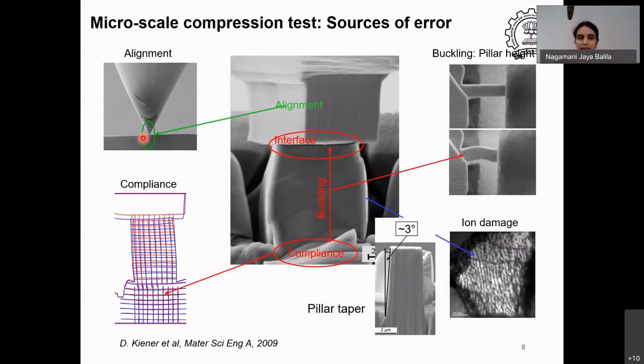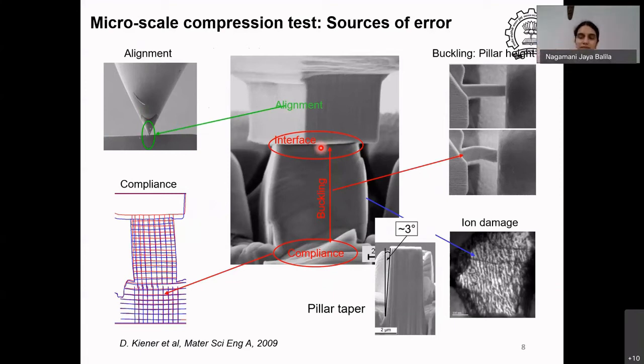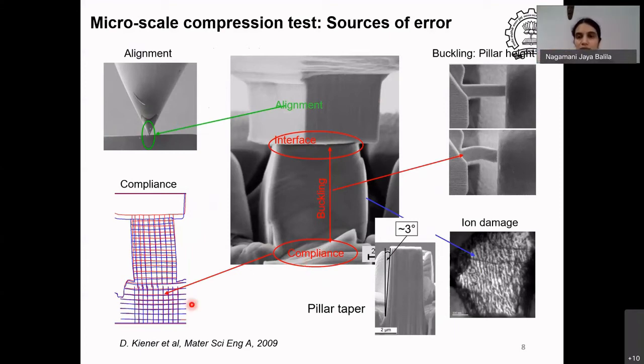One problem is that because the sample is so small, it is still held to the bulk and you have to paste the bulk sample onto something. If that pasting is not straight and perpendicular to the punch, you will have a tilt, and the contact initially made may not be exactly flat with respect to the sample. Then there is the issue that the pillar is still attached to the substrate, so the springiness of the substrate also contributes to the deformation — this is called compliance.